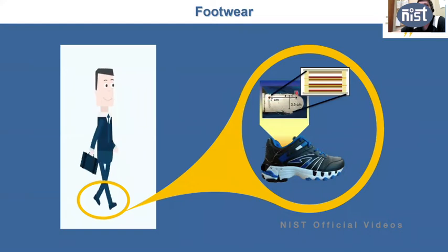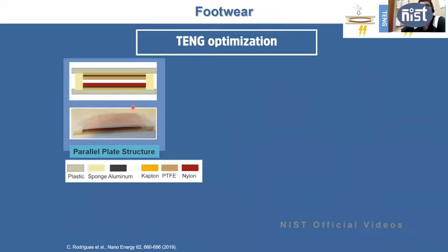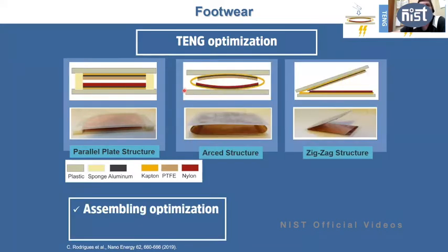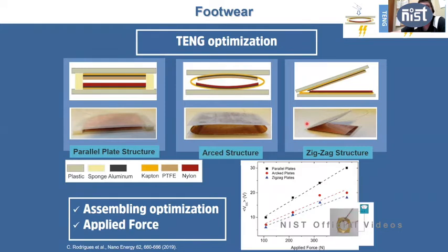So with this area, we can put a triboelectric nanogenerator there. This is what we have done. We have optimized the configuration that you can put inside, not only the size, but what we can do with these materials. This is very simple, a structure that looks like this. Here is one of the triboelectric materials, in this case Teflon. On the other side is nylon. You have the 2 electrodes on the top and at the bottom. The other structures are similar, but instead of these 2 parallel plates, you can have an arced structure, or a zigzag structure like this, where you can put multiple steps. We have optimized this assembly, and what we found is that the parallel plates are typically the best for this particular application.